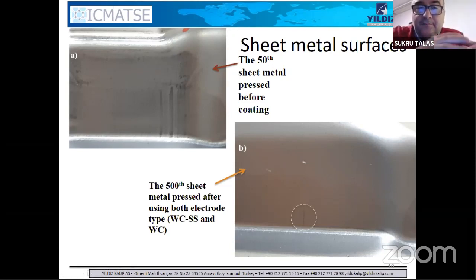Although it is hardened, after 50 sheet metal processing, the surface is coated with metal from the sheet or pieces. Those pieces are causing adhesive wear on the sheet metal and also the die mold surface. So those stretch marks are created because of the die. If the die surface is not clear, or it has some asperities, some defects, these problems occur. The problem is that these can result in rejection of parts. So a company might say, okay, this is too much, send me another part which is better.